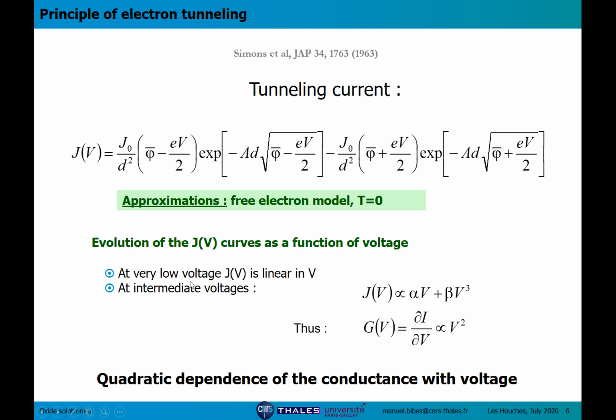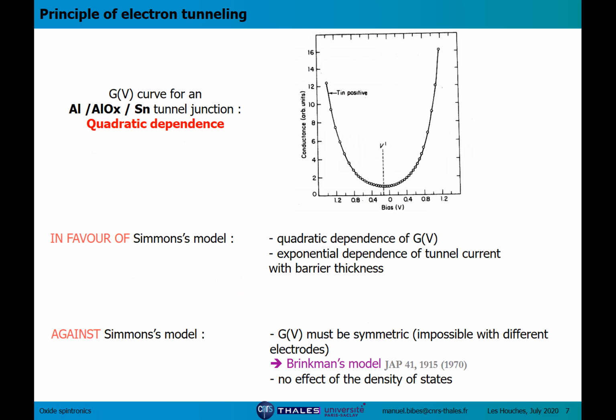So there are several important features from this equation. At very low voltage, the tunneling current is going to be linear with the voltage. So very low voltage, meaning a few millivolts or lower. And at intermediate voltages, it is going to be proportional to a linear term plus a term that goes as the cube of the voltage. So that the conductance, which is the derivative of the current or the current density over the voltage, is going to be proportional to V squared. And this V squared dependence of the conductance is one of the hallmarks of tunneling, okay, direct tunneling. And here is an example of this. So this is a result from the 60s in junctions that have two different electrodes.